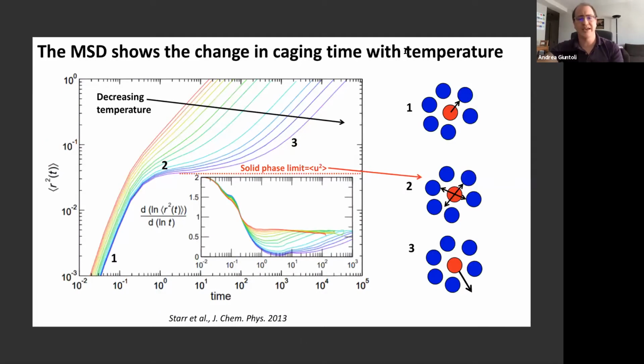You can see actually this behavior in the mean square displacement again. If I go to this system that I showed, this curve that I showed before, and I see the effect of decreasing the temperature, you'll see that after the first ballistic regime, you have this plateau, which is phase number 2, this caging dynamics, where you measure the Debye-Waller factor. And then after a while, you see the breakdown of the cage. That's phase 3, which happens at later and later times. In fact, if you have a solid, phase 3 will never happen. You just have vibration of your particles around their equilibrium positions. So you just have a limit for the solid phase.